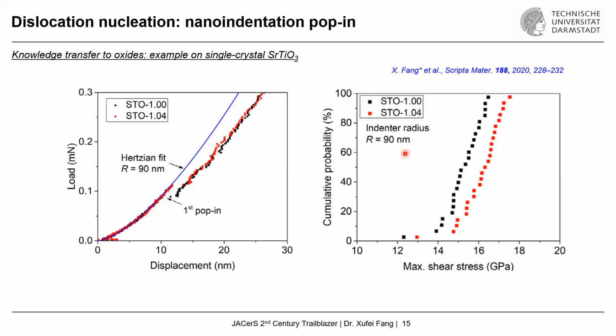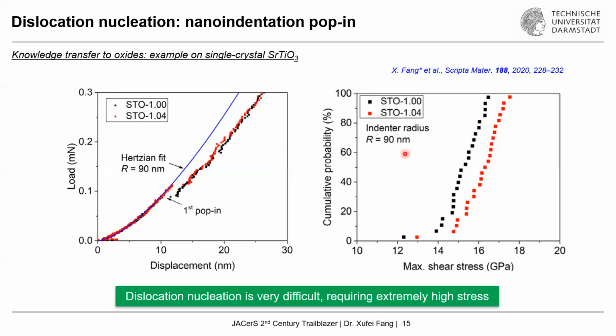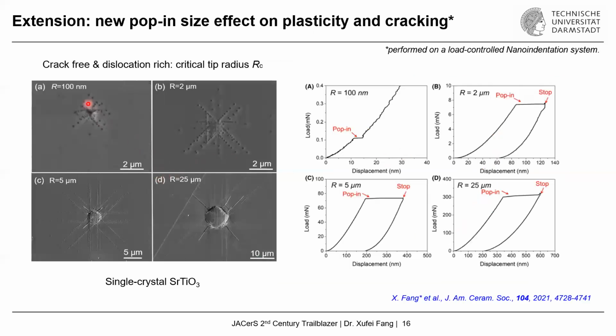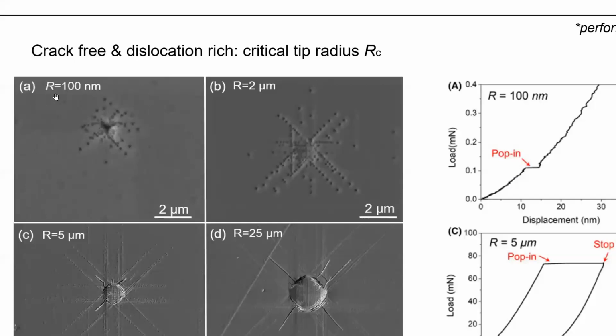So what does this mean? Can we also just directly transfer the conclusion from metals, saying this corresponds to dislocation nucleation? We need to be sure about that. So we went ahead and even tested different tip radii here. For example, 100 nanometer, 2 micron, 5 micrometer, and 25 micrometer.